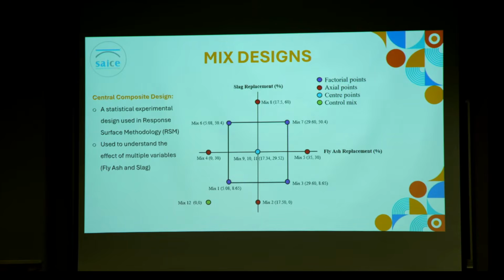To design the concrete mixes efficiently, a central composite design was used. This was a smart statistical method that allows us to get a range of results for the concrete mixes while only casting specific mix designs. So for those wondering how I got the mix designs from a square, each coordinate on the square corresponds to a specific mix design to be tested. The central point denotes the central mix, which was cast 3 times, and the corner and axial points captured the extreme and intermediate levels of cement replacement. A total of 11 mix designs were obtained from the central composite design, with the 12th mix containing no slag and no fly ash to serve as a reference.